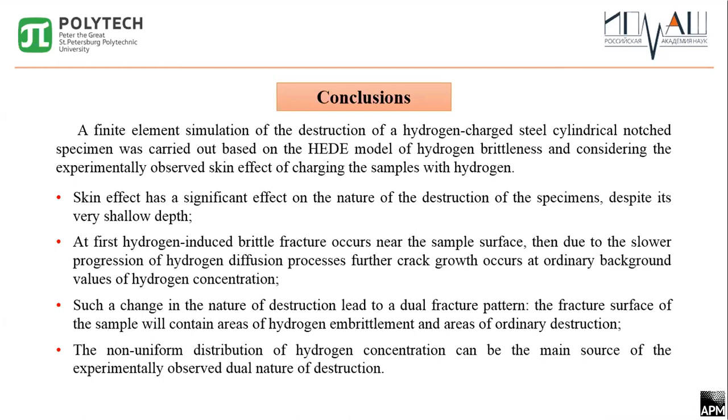We carried out a finite element simulation of the extension of a hydrogen-charged steel cylindrical notched specimen. The calculations were performed on the basis of the HEDE model of hydrogen embrittlement, taking into account the experimentally observed skin effect of charging the samples with hydrogen. We found that this effect has a significant influence on the nature of the fracture of the specimens, despite its very shallow depth. The simulation results showed that in this case, at first, hydrogen-induced brittle fracture occurs near the sample surface, and then ductile growth occurs at ordinary background values of hydrogen concentration due to slower progression of hydrogen diffusion processes. Such a change in the nature of fracture leads to a dual fracture pattern.